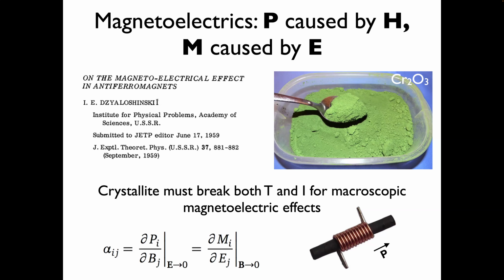And so the crystal has to break, generally, the classic case has to break both time reversal and inversion symmetry for macroscopic magnetoelectric effects. The most famous magnetoelectric is Cr2O3, which was actually the very first one that was pointed out. These are the symmetries of this material for maybe experimentalists. Cr2O3 has the same crystal structure as sapphire, but instead of aluminums, they're chromiums. So it's a commensurate antiferromagnet. And it was the first material that Dzyaloshinskii pointed out could be a magnetoelectric system.